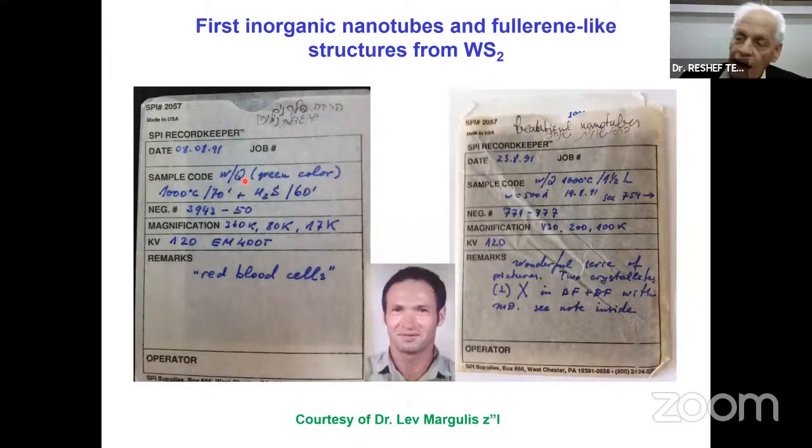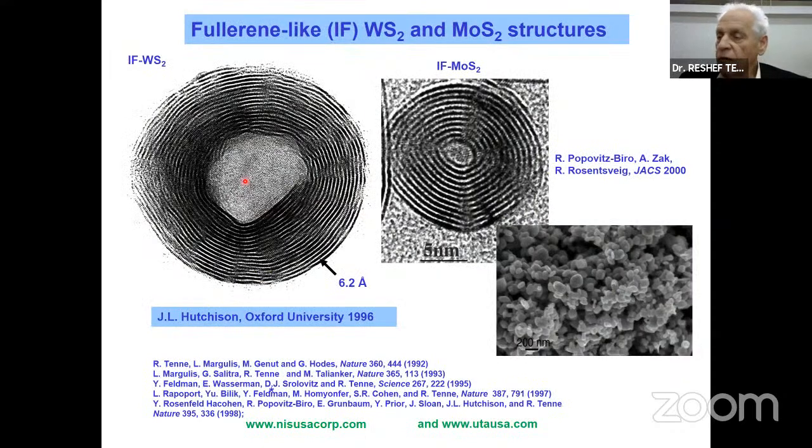So these are the analogs of fullerenes, but now in molybdenum disulfide and tungsten disulfide. And the question is, why do they form? It is clear to you now because you understand that these materials suffer from very reactive edges which do not support these dangling bonds, and they have to fold up and close into hollow closed structures.